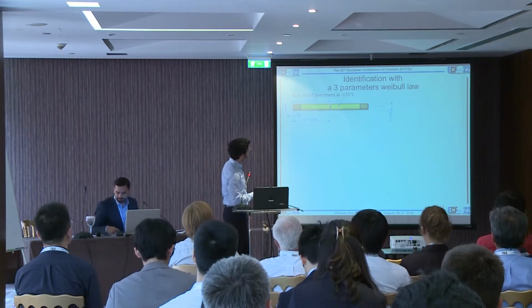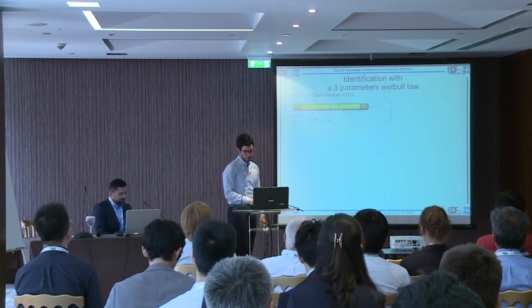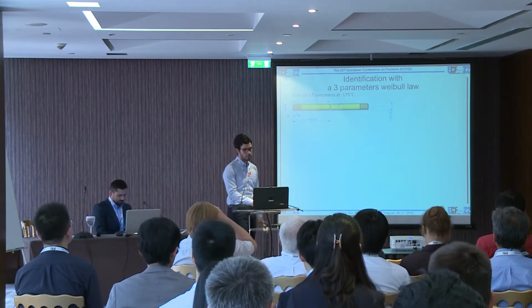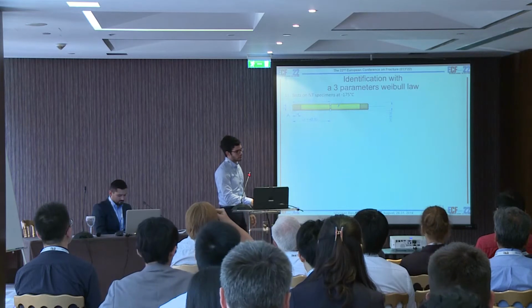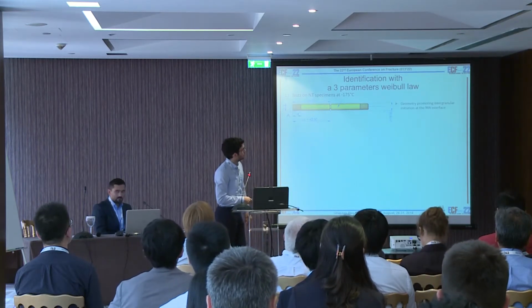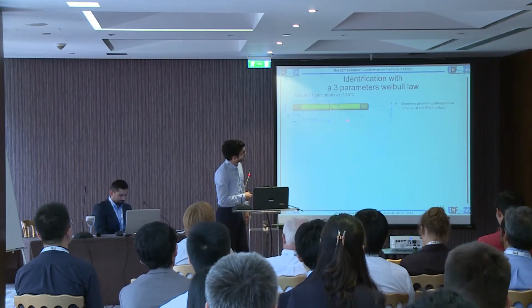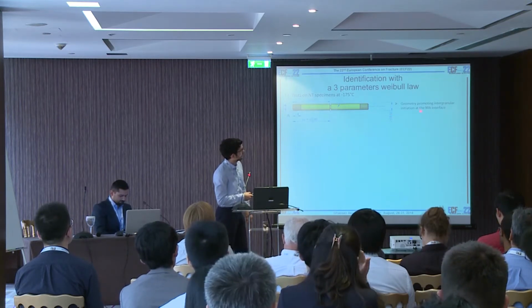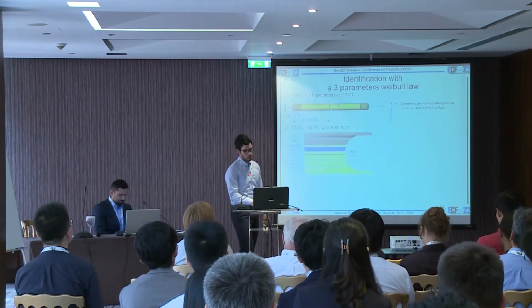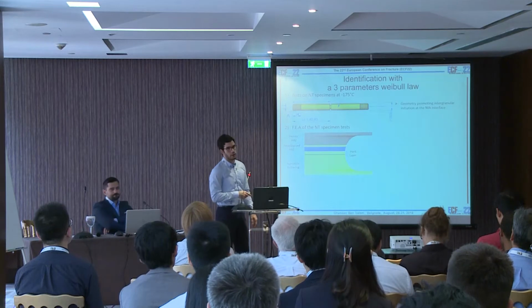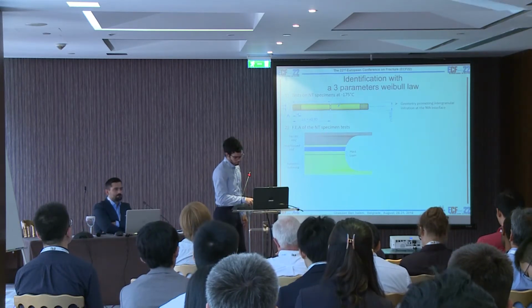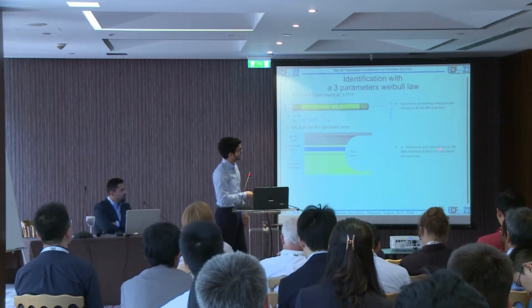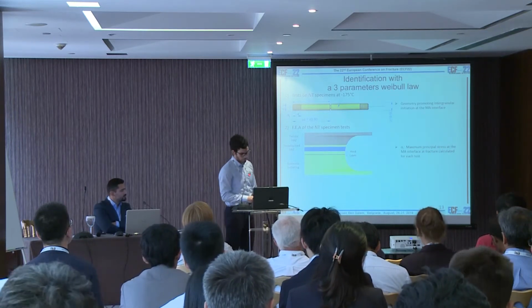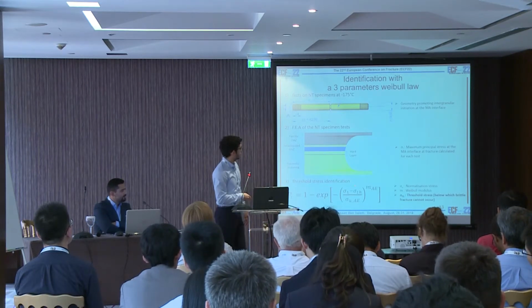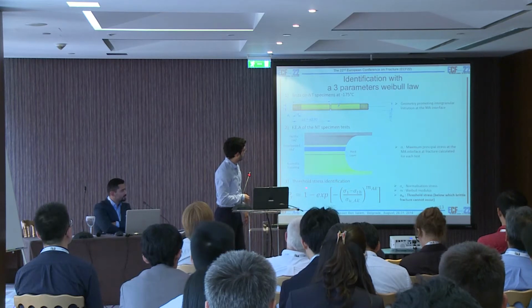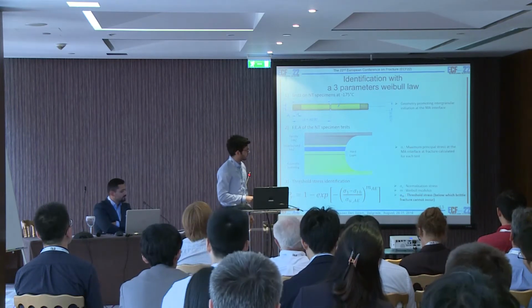So in the last part, we will focus on the identification of the threshold stress. So a suitable way to do so is by testing notch tensile specimens at very low temperature in order to minimize the plastic deformation. And we have to choose the geometry configuration which promotes intergranular initiation at the MA interface. The second step is to do a finite element analysis of this NT specimen in order to calculate the maximum principal stress at the MA interface at fracture for each test. And finally, we try to fit the data with the 3-parameter Weibull law in order to calculate this threshold stress.